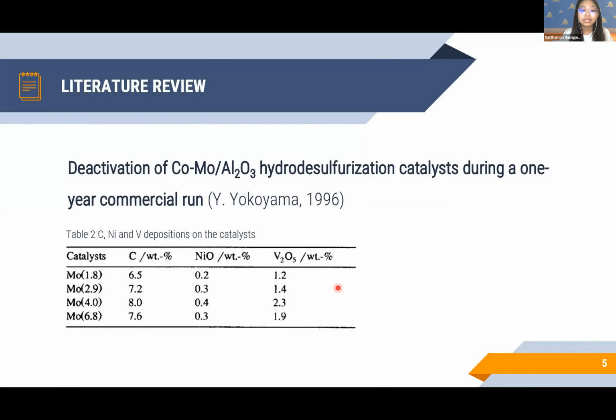Next one, this paper studies a series of cobalt molybdenum on alumina oxide hydrodesulfurization catalysts during a year of commercial run. The study covered catalysts with different loadings. According to the research, it was found that the active sites of cobalt molybdenum sulfide are located at the edge of the molybdenum disulfide layer decorated with cobalt.